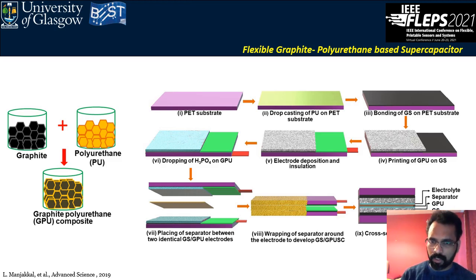We use it as a current collector and bonded on the top of this substrate, and then the graphite polyurethane is printed. And then here, on one side, we attached the electrode and insulated it with the polymer. And then here we used phosphoric acid as an electrolyte for the supercapacitor. And there are two types of such electrode. We made such electrode, and then